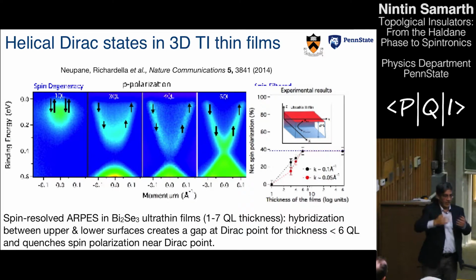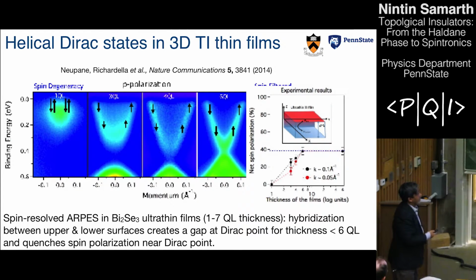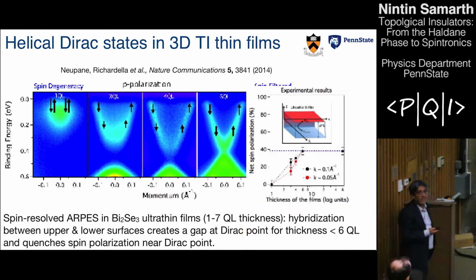And when they couple, they hybridize. And when they hybridize, you open up a gap. So what happens is that as you go from samples which are about 7 nanometers, so QL refers to quintuple layer, that's a unit cell, it's about 1 nanometer. As you make a thin film thinner and thinner, you find that this point over here, the Dirac point as we refer to it, opens up, it's disrupted, and you get an energy gap over there. And that energy gap is because of the hybridization of the top and bottom states.